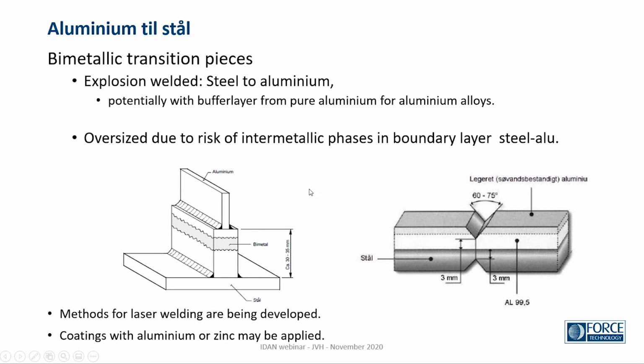And for an application using the explosion welded combination of steel and aluminium, the transition pieces are used to weld together, like ship hulls and the upper part of the ship, which might be in aluminium. As we started to say, you can't weld them together directly, so you need to have some transition between them. And you can use the explosion welded plate, cut it into